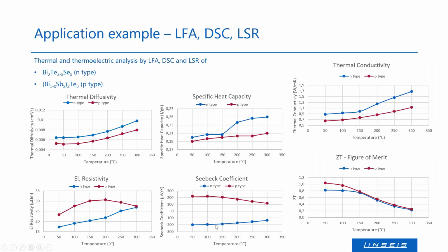Using all those values, one can first determine the thermal conductivity. With the thermal conductivity and the electrical properties, one can then determine the figure of merit, where one can clearly see that the P-type sample has, at the lower temperatures, a higher figure of merit, whereas at the higher temperatures, the N-type and the P-type show a similar performance.